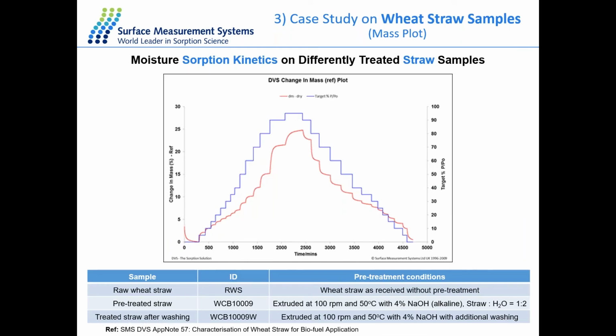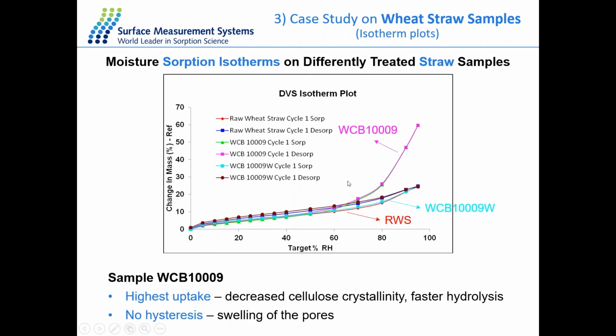So here the experiment we perform is a very typical water sorption from 0 to 95% RH with 10% step at 25 degrees. And here we have 3 different samples: the non-treated straw sample, the treated straw sample with some alkaline solutions, and another treated sample after alkaline, we have an additional washing step at the end. And we compare the mass plot of 3 different samples.